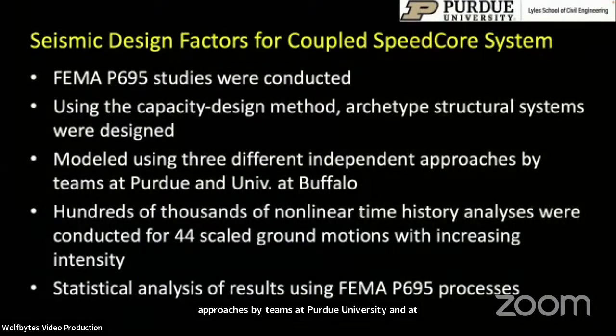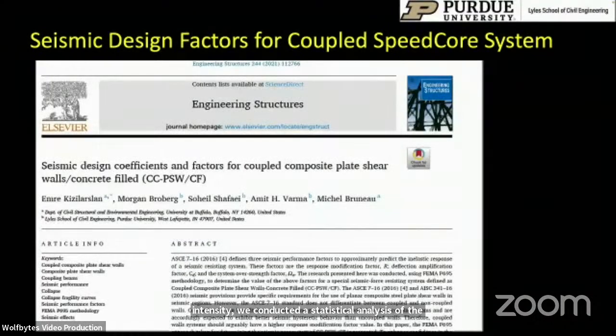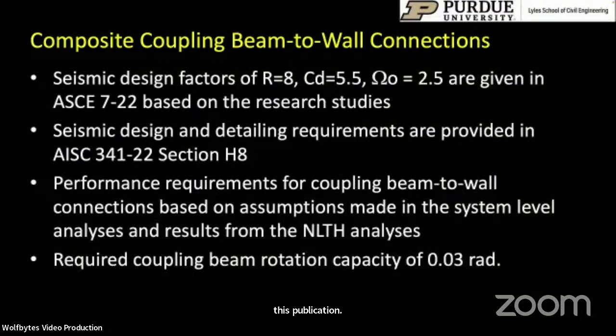And we did hundreds of thousands of nonlinear time history analyses for 44 scaled ground motions with increasing intensity. We conducted a statistical analysis of the results from the FEMA P695, and the results from all of that are summarized in this publication. And eventually, all of this research was presented to the ASCE 7 committee, to the Seismic Structures Committee, and also to the Provisions Update Committee, which reviewed it, provided comments, and accepted it into ASCE 7 with an R factor of 8.